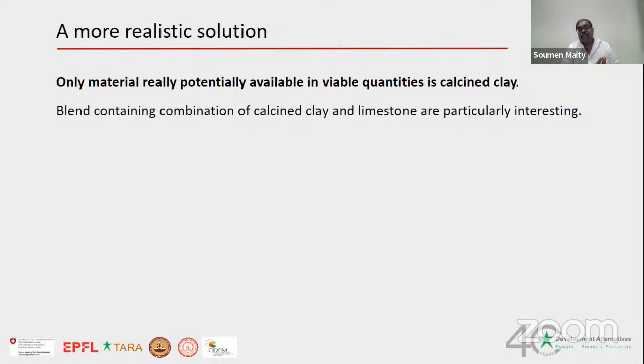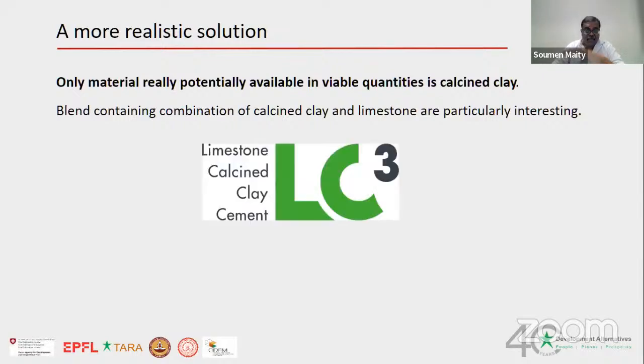The clay that we are talking about in a cement plant is any clay which has kaolin content of around 40% is suitable. And that clay is available in plenty. We have been doing surveys across the country, and till date, we have not failed in finding it anywhere. So a blend of calcined clay and limestone, as Professor Scrivener pointed out, is very interesting, and that brings us to the question of LC3.